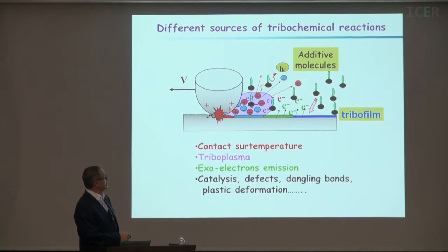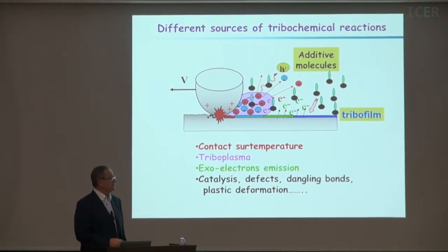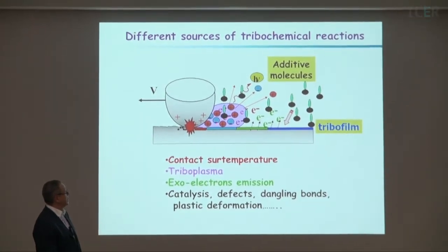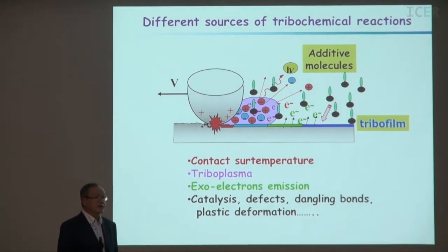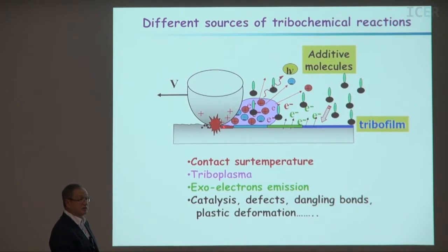The second point is that if the two materials are not insulating, you can have charging of the two materials and a plasma discharge in this area. This has been shown by Professor Nakayama in Japan. It's very, very well documented. This triboplasma can modify the surface chemistry behind the contact, but also inside the contact, and maybe sometimes before the contact. After that, a little bit further from the contact area, the surface has been tribostressed, and electrons can be emitted from the surface during a certain time. We call this exoelectron emission. These electrons can react with the molecules of the lubricant and change the surface chemistry again.